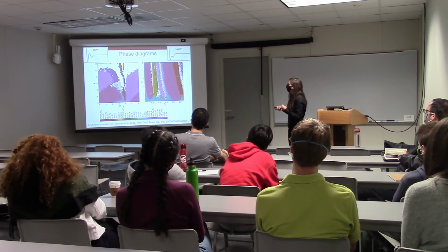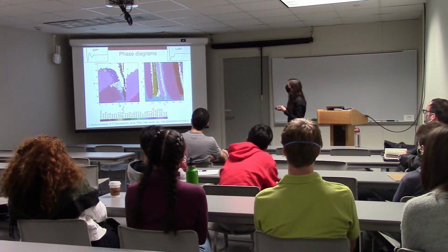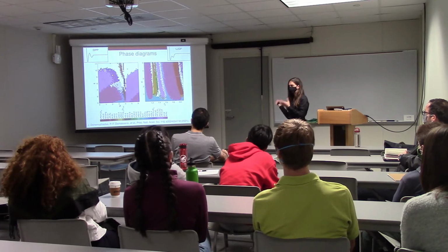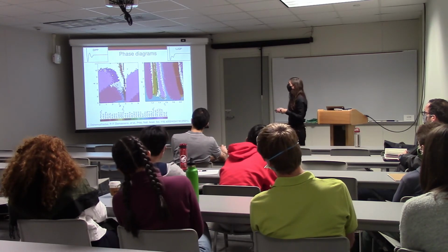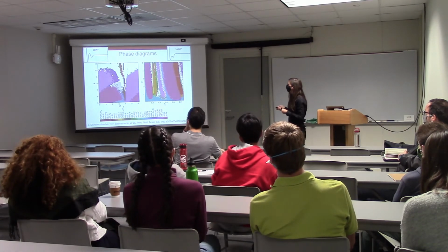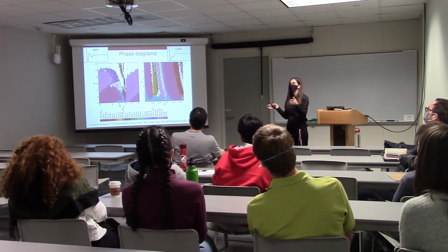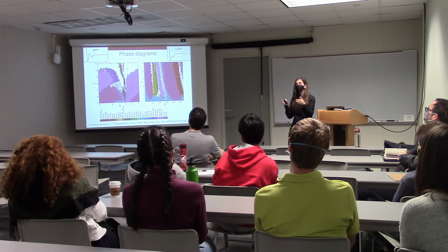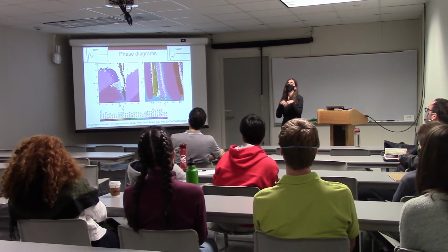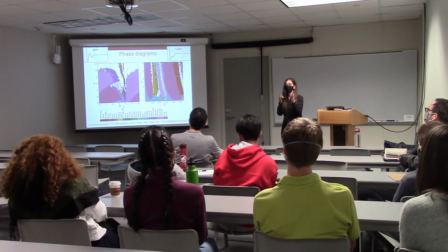investigate those. But you can see, hopefully, that some of these colors are the same in both the systems, so some of the structures form irrespective of the specific shape of the interaction potential. And you see that some of them are really close together. Like you have a lot of phase variety in small regions, and that is also mimicking what happens in a lot of intermetallic systems when you have a lot of phase variety in a very small compositional space.